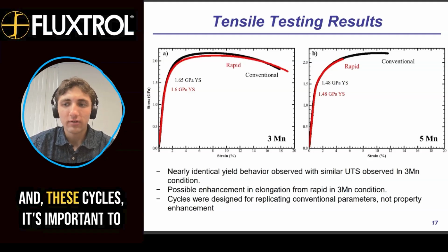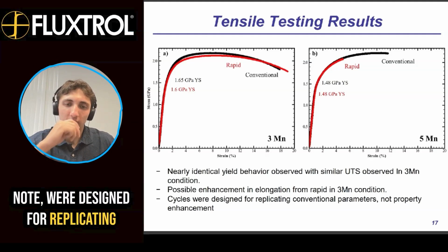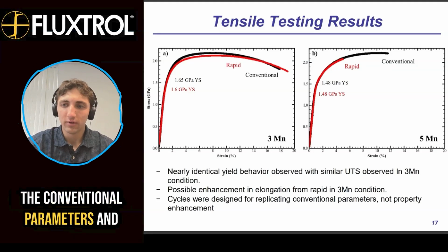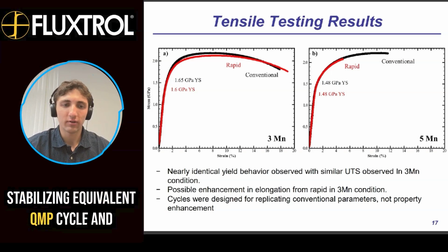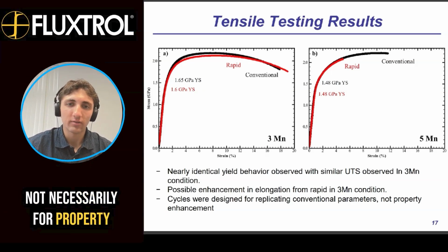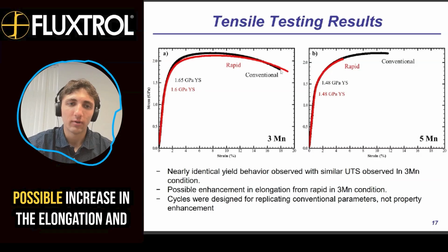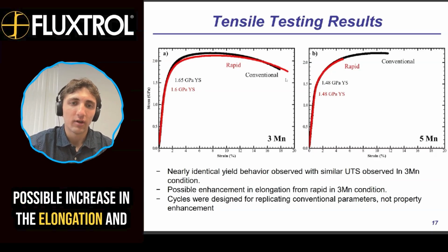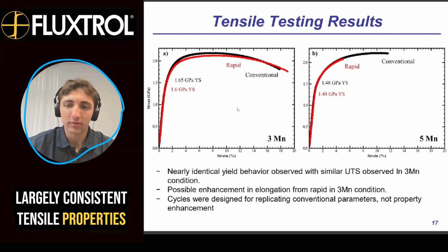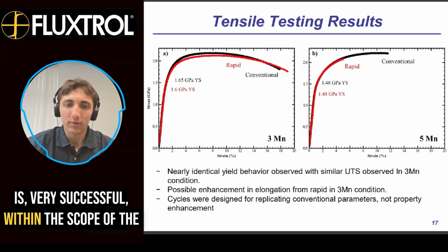And these cycles, it's important to note, were designed for replicating the conventional parameters and stabilizing an equivalent QMP cycle, and not necessarily for property enhancement. So the fact that we're seeing a possible increase in the elongation and largely consistent tensile properties is very successful within the scope of the project.